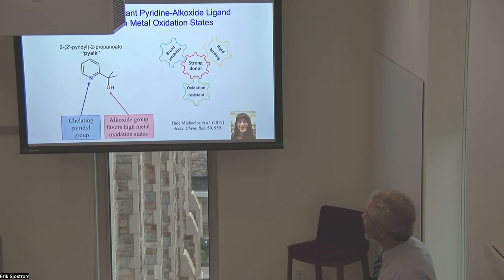However, what we want is something that is oxidation resistant and stable and stabilizing high oxidation states. And we explored a variety of different kinds of complexes. And this ligand, the so-called pyalk ligand or pyridine alkoxide, this is the name of it, if you want the full chemical name, has been the winner. And it combines some very good properties. It's a strong electron donor, so that helps to stabilize high oxidation states. It has very good solubility. It has very strong and rigid binding. It has this chelating group. It's oxidation resistant. And it also combines this alcohol group, which can dissociate a proton in a high oxidation state. So it can carry out what's called proton-coupled electron transfer, which helps to modulate and make easier the oxidation reactions.